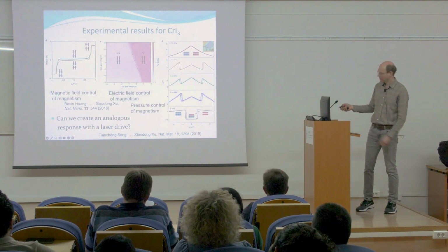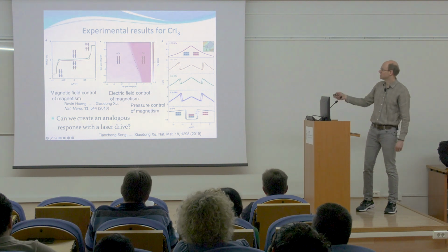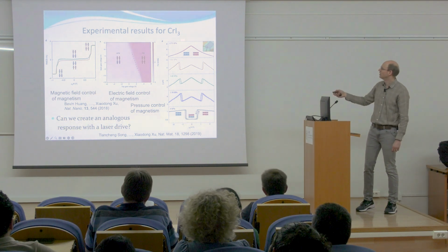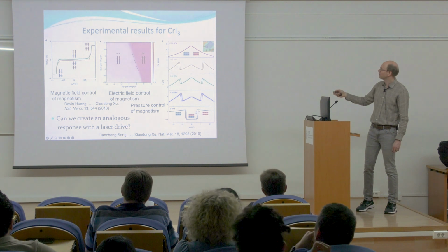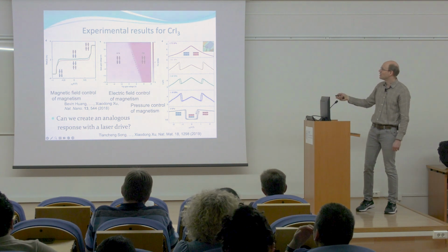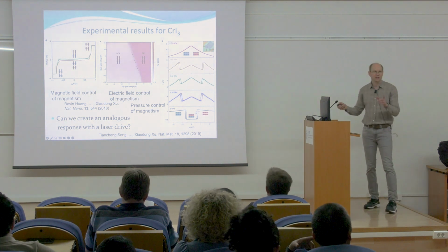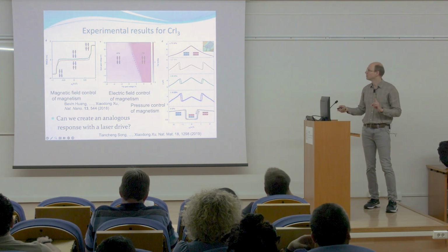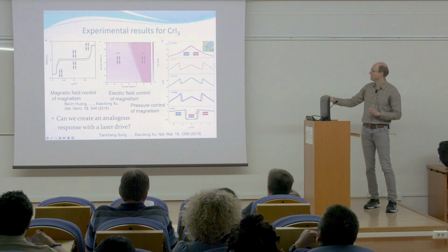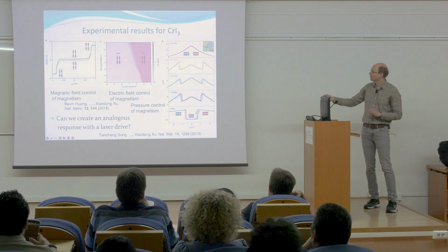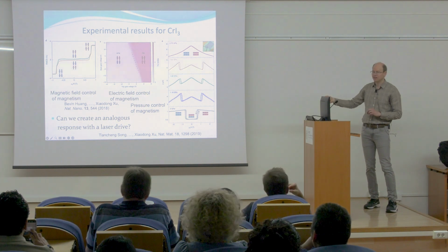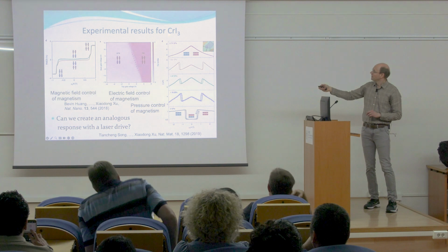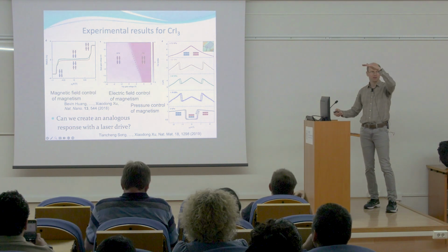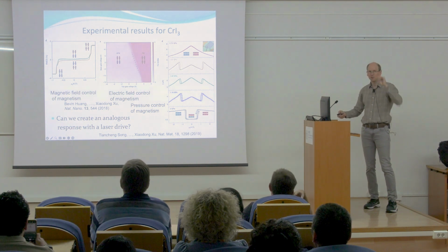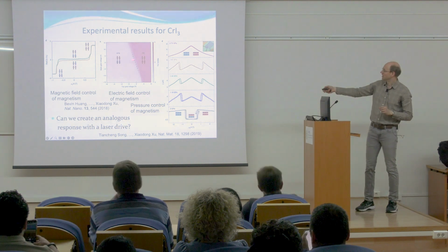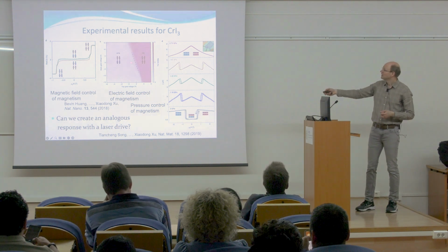And so since I'm about out of time, let me just kind of summarize the sort of things we can do. So there's a material, chromium triiodide, which is known to have a very small energy difference between different magnetic configurations, an antiferromagnetic configuration and a ferromagnetic configuration. So this is a material which has a layered structure. We can just look at 2 layers, which is what's done here. So it's called bilayer.